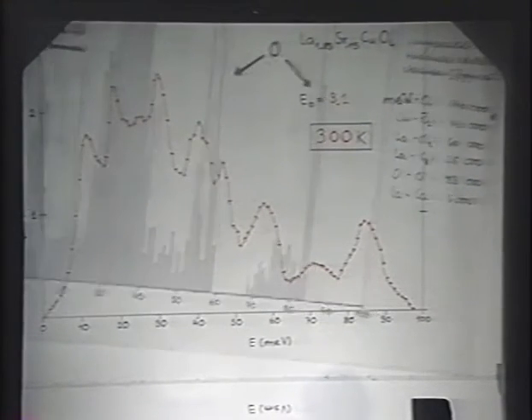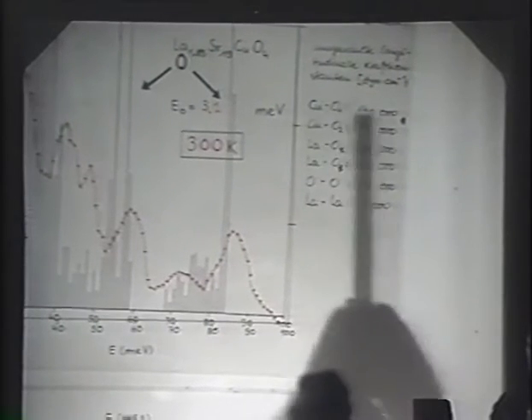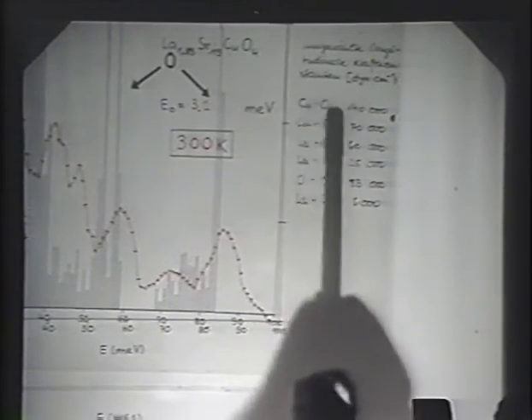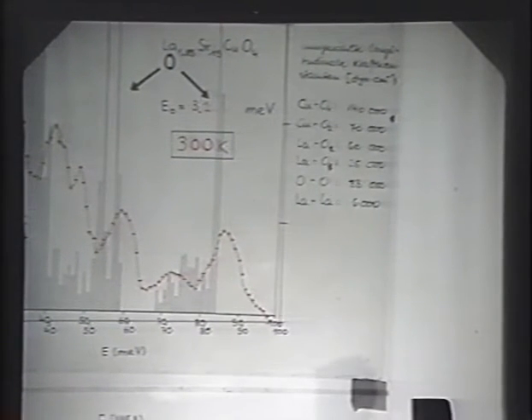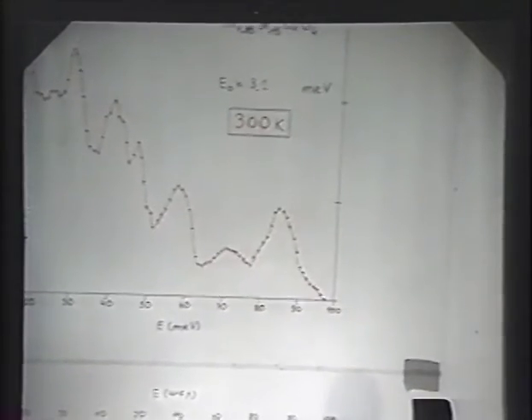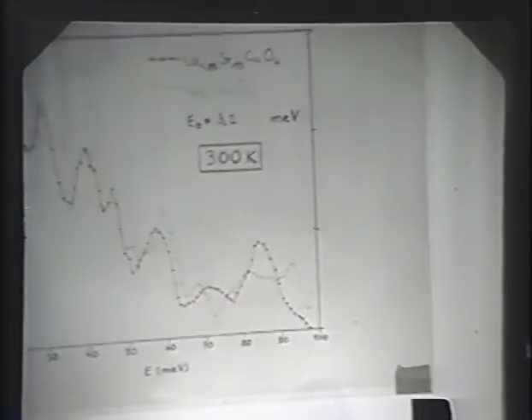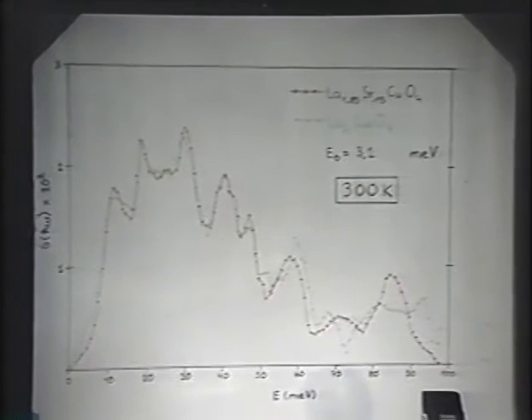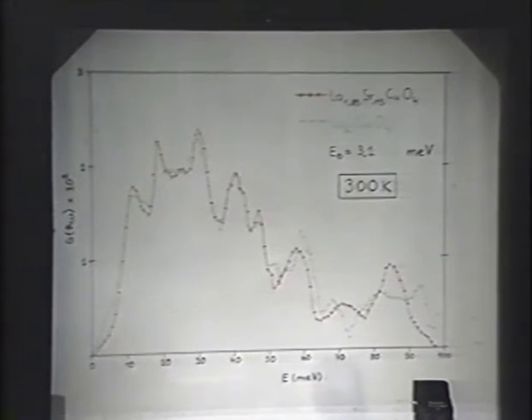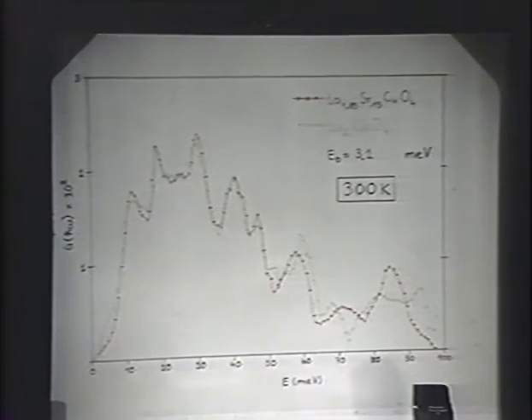sample to sample. I may also say shortly that in this Born-von Karman model it was necessary to use very high force constants for the copper O1 coupling constants, over 140,000 dynes per centimeter. Okay, here I compare this room temperature data with the phonon density of states measured for the non-TC sample.